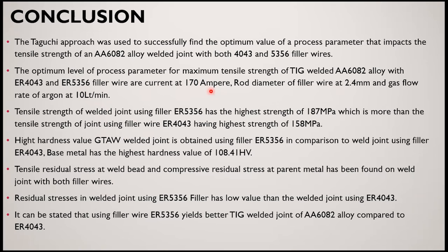Next, the tensile strength of the weld specimen with 5356 is 187 megapascal, which is more than the weld specimen with filler wire ER4043, which has a strength of 158 megapascal. We are also getting a high hardness value with filler wire 5356. Next, tensile residual stress exists at the weld bead and compressive residual stress at the parent metal, which is also suggested by various researchers.